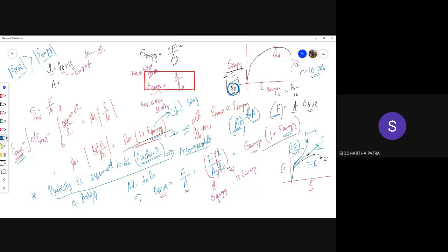But let's say in tension, because the cross section is reducing, once you go past that ultimate stress point, the net load bearing capacity of the specimen, not the material, just the tensile specimen, because it is under tensile loading, reduces. But you do not recognize that it's the cross section that has reduced, because in the engineering stress strain diagram you are still using the original cross section area. Therefore you perceive it as the falling of the stress, going from ultimate stress to a smaller stress where it fractures.